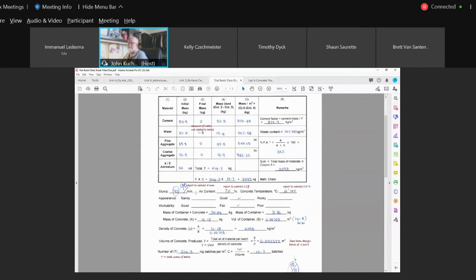They did an air content test. It was 7%, and they wrote 7, but you have to report it to the nearest 0.1. If you don't write 7.0, I don't know that you know it's to the nearest 0.1—for all I know you might think it's to the nearest 0.2. So you've got to put 7.0. This is to the nearest 0.1%. If it's 7.1, then it's 7.1; if it's 7.5, it's 7.5.